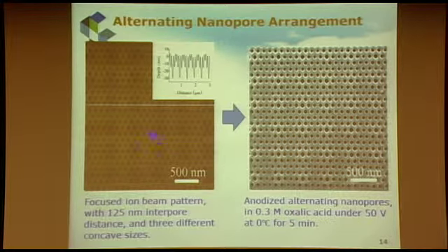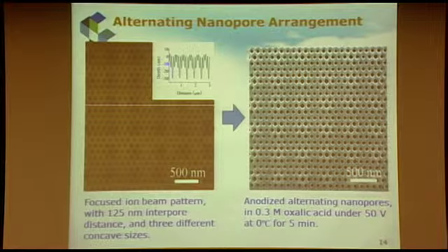This is pretty easy to do using the microscope. So you see here we did some AFM measurement. We can see deeper pores and larger pores and small pores, shallower pores. We know that from the changes of these peak locations, we can calculate the pore distance, which we already know. But the idea to show you here is you can start with different size or depths of pores.